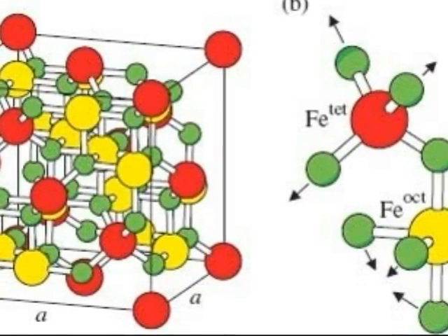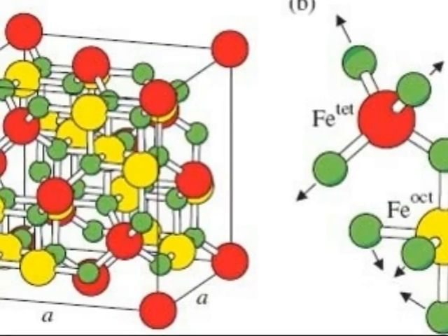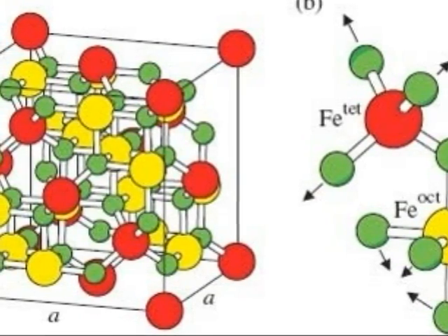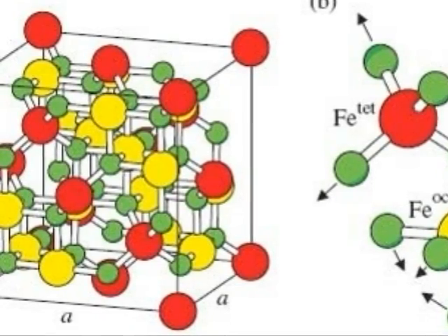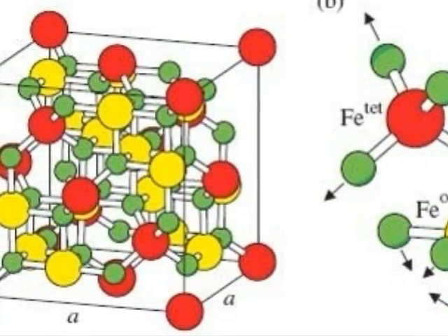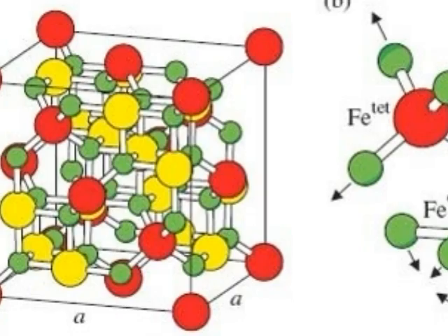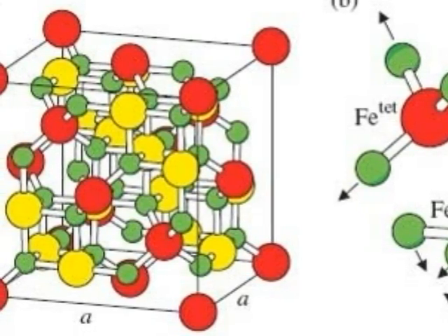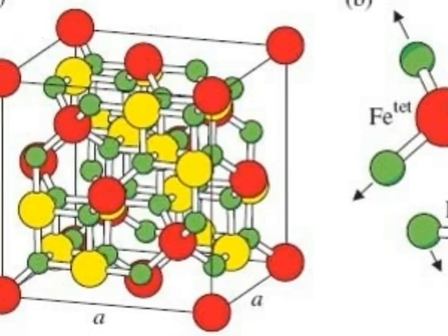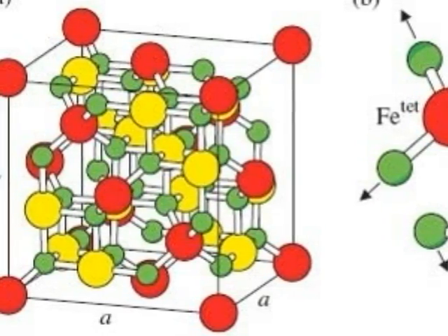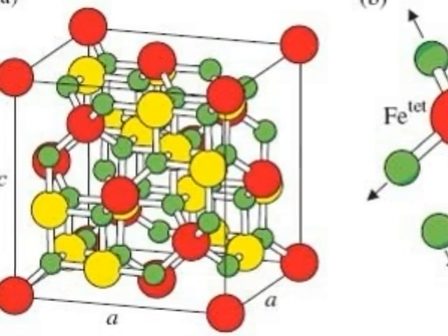A co-precipitation method is used to produce ferrite particles. In this method, solutions containing iron 3 and/or iron 2 are used and combined with a base to form ferrites, such as magnetite, a non-toxic compound of iron oxide. Magnetite is an isometric hexoctahedral crystal. It has both octahedral and tetrahedral crystal sites, which forms a spinel-like structure.